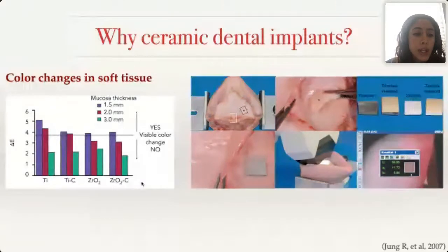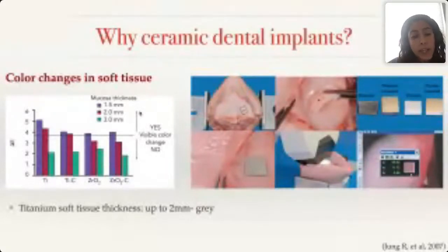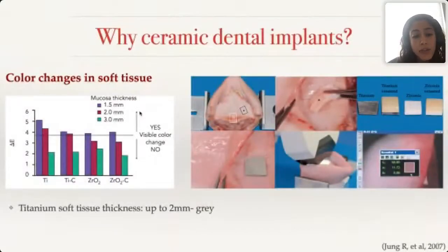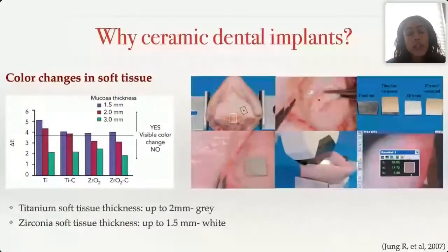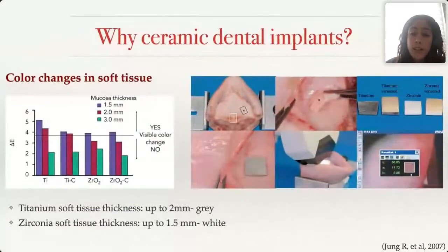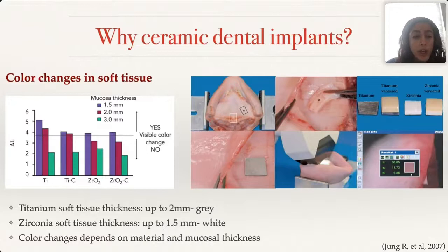This bar chart shows the changes in the color, and this line shows the level from where the naked eye could see the color changes. Basically here they found that with titanium, soft tissue of up to 2 millimeters still showed grayness. So even that much thickness in this situation showed some color changes. For zirconia, up to 1.5, it was still white. So they concluded that the color change depends on the material and the mucosal thickness.